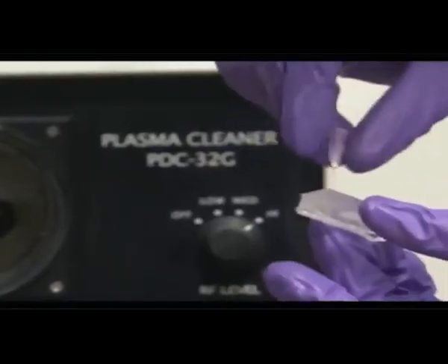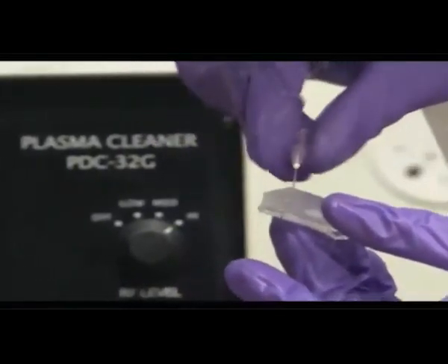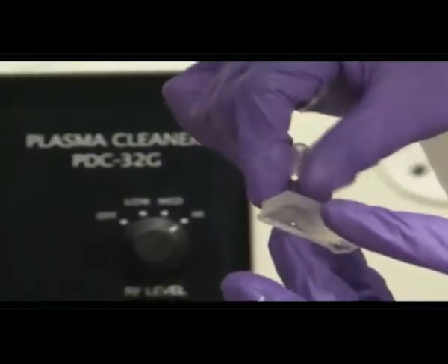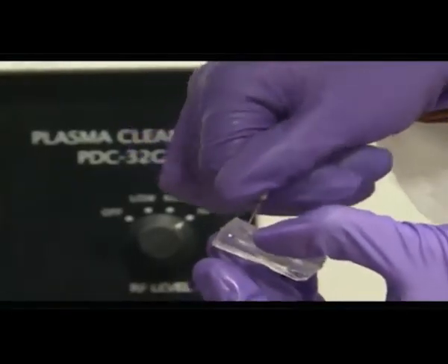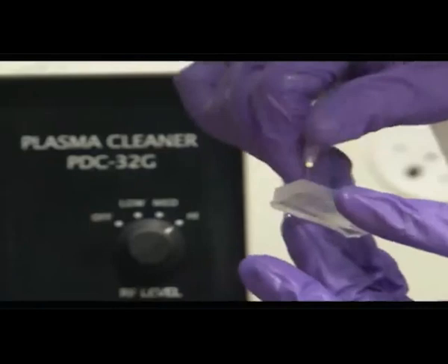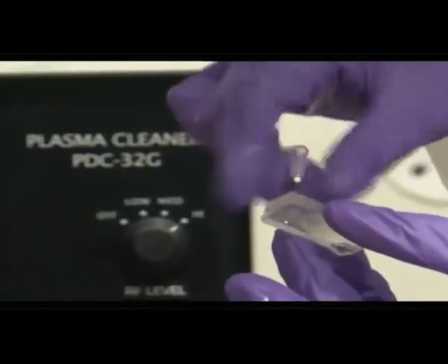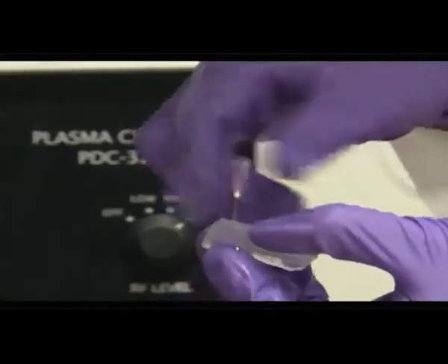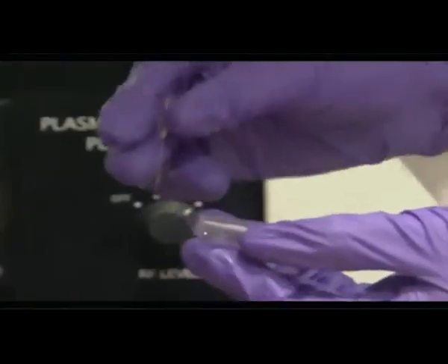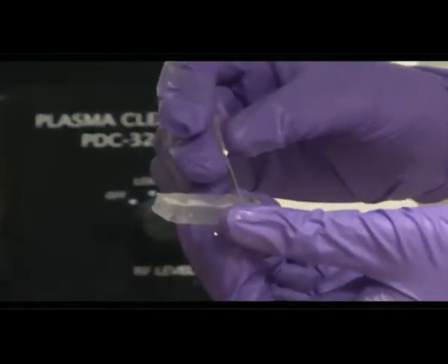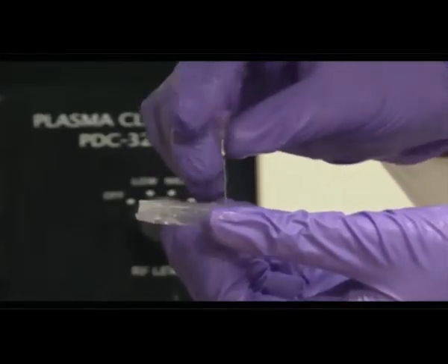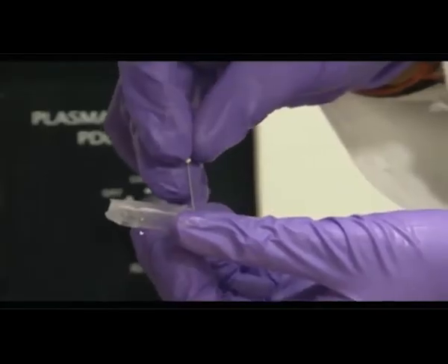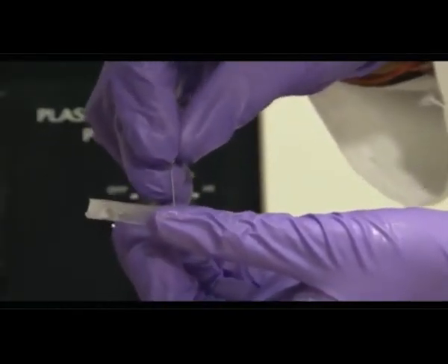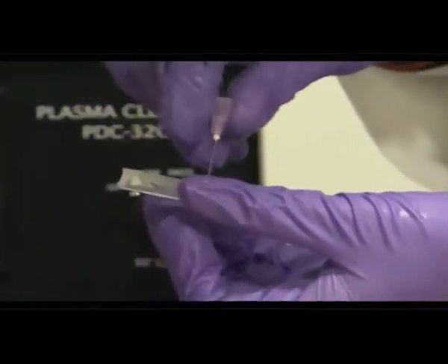So you now have needles pricking holes on both sides of this device. The fantastic thing about this is it's a rubbery material, so whatever small channel has been created across the thickness of this PDMS can be easily cut. The advantage of PDMS is that it is a highly elastic material, so if you put a small piping or tubing inside this drilled hole, there is always a tendency of a self seal between the PDMS and that tube, and therefore you can easily, in a very leak proof manner, handle fluids into this small structure which has been embedded on the bottom of this PDMS layer, and closed subsequently by a glass wafer.